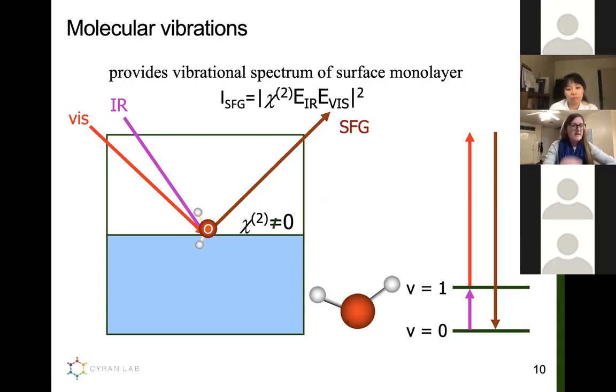And so a break in the symmetry, you can think about this as being in certain crystals, but this break in the symmetry is inherently also at an interface. You can think about, again, my water here. So the surface of the water is different than the air above it, right? And so at that surface, we can generate an SFG signal because there's a break in that symmetry.